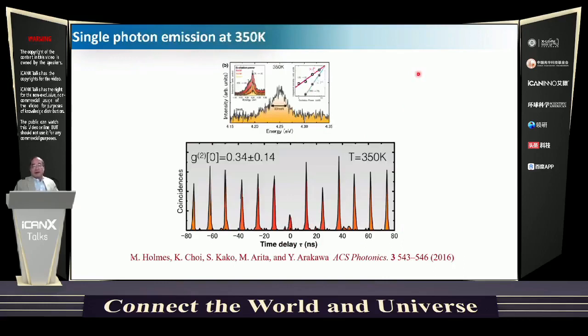We also elevated the temperature up to 350 Kelvin, and we see the anti-bunching effect even at this very high temperature. This is the temperature at which you can have it operate.